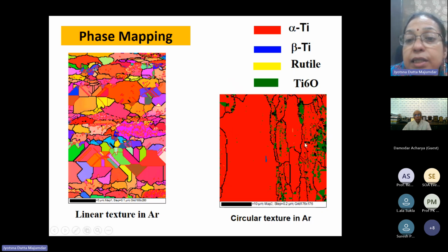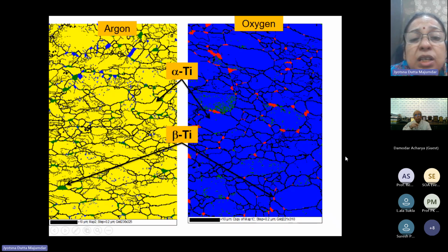A circular texture surface again. This is the texture surface. We find the cross section we are observing actually. Here also you see that rutiles are very less, but this is mostly alpha and Ti6O phase formation. So phase stoichiometry varied with different samples actually.